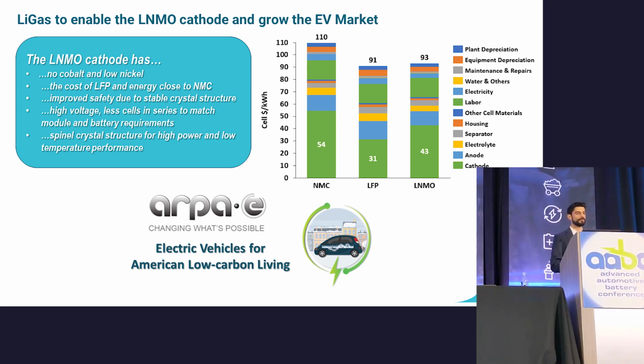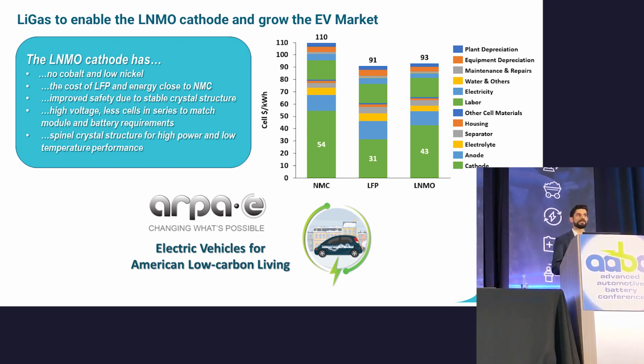For those of you that don't know, the LNMO cathode is a high voltage spinel, has no cobalt and a very low nickel content, which means it's very low cost, about the same cost in dollars per kilowatt hour as LFP, but has the watt hours per kilogram of NMC materials. So it's the best of both worlds.